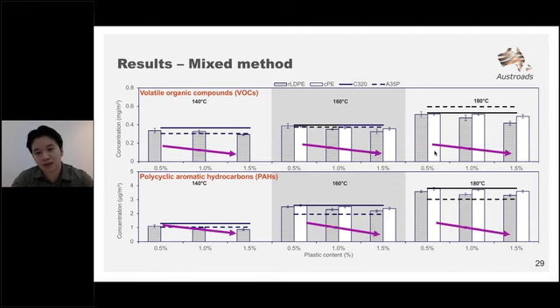However, from a plastic content perspective, as plastic content is increased, we also see a difference in emission concentration output. Comparing the emissions obtained from C320 at 180 degrees Celsius, reduction rates go up as high as 30% and 20% in VOCs using recycled LDPE and CPE. And from a PAH perspective, the reductions were there, however, not as significant as the VOCs, and the reductions were up to about 13% and about 8% for 1.5% RLDPE and CPE.